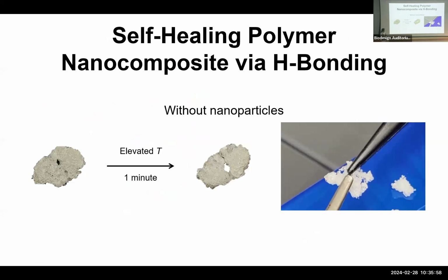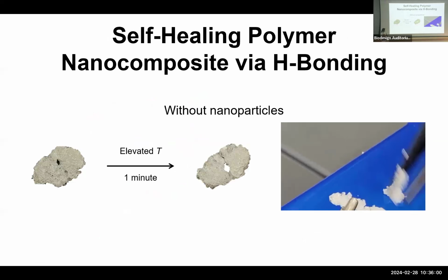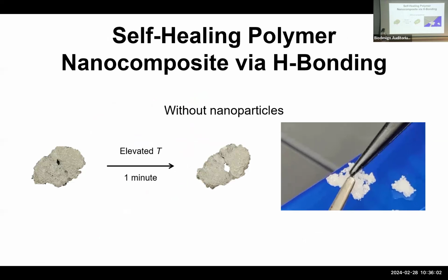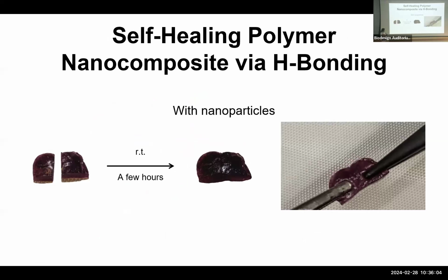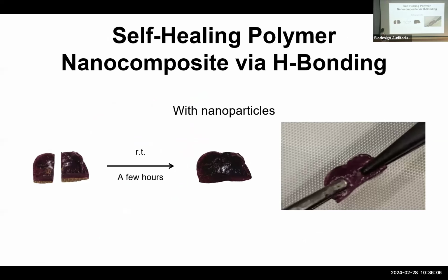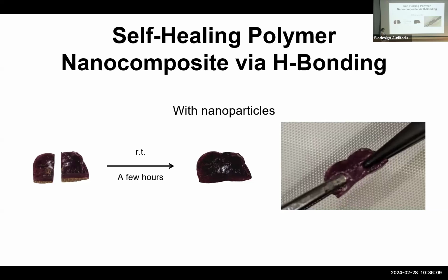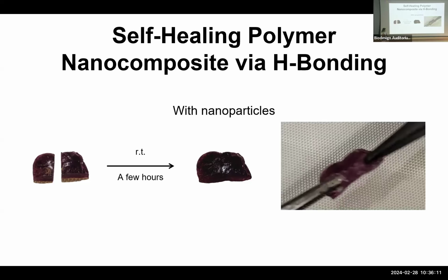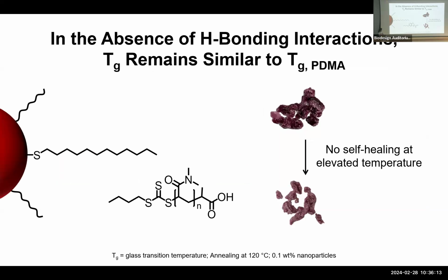As a demonstration, these polymers alone without nanoparticles don't have self-healing ability. But by adding these nanoparticles, now you can self-heal these materials. And of course, we have to prove that it is due to that interfacial engineering. So we also functionalized nanoparticles with dodecanethiol, which is not able to form hydrogen bonding interactions. And we see that these are not self-healing, and we also don't see a change in glass transition temperature.